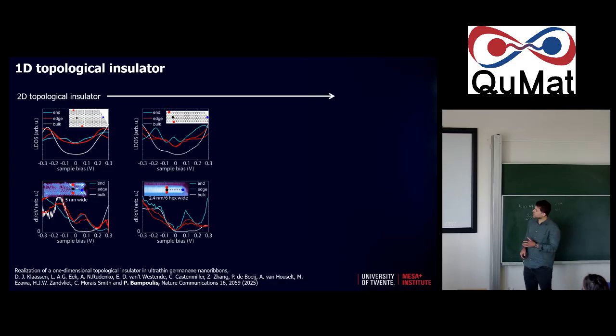Okay, so if we go now to a narrower nanoribbon, so now we talk about a 6 hexagon wide nanoribbon, we see in the theory that the edge states have a little gap-like dip around 0, whereas that doesn't happen at the end. So the end still is very prominent.